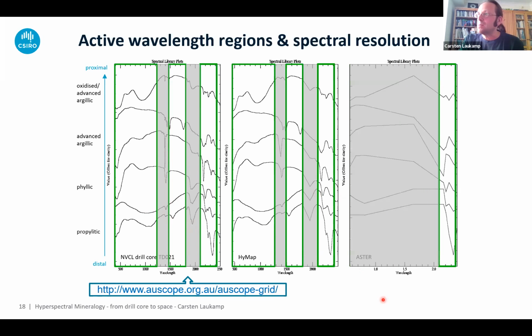The other challenge is that many remote sensing instruments are just multispectral. And in the case of ASTER, that's actually what you're left over with in the shortwave infrared: 5 bands here. So not much you can work with, but it's still actually good enough. You can still distinguish, let's say, chlorite from white mica, from amphibole and so forth. You can still do this with ASTER, even though you have just multispectral resolution, just 5 bands that you're left over with.